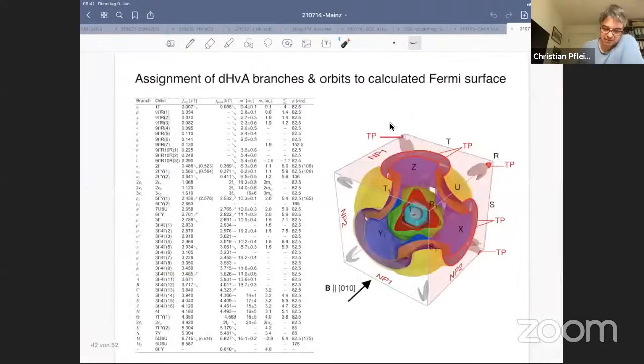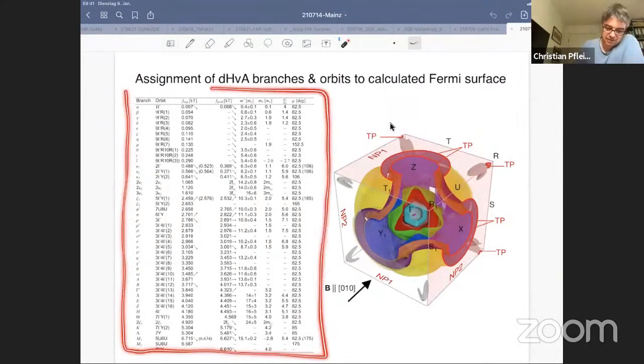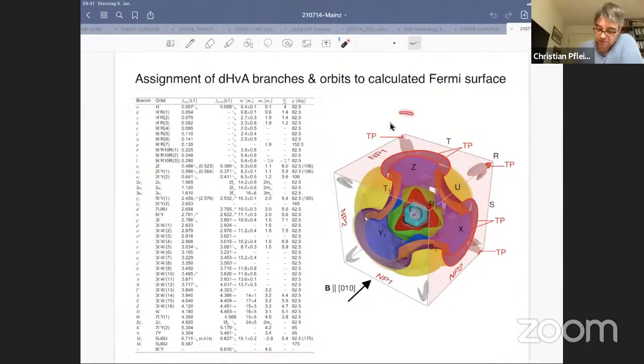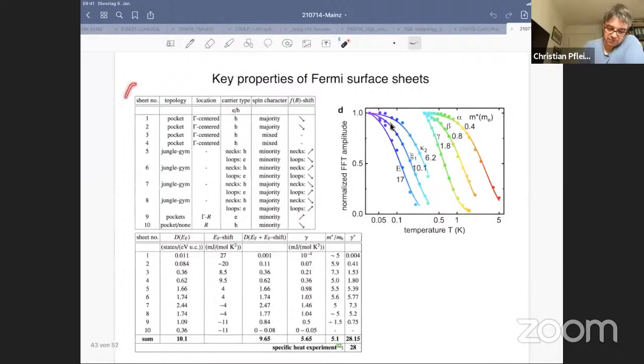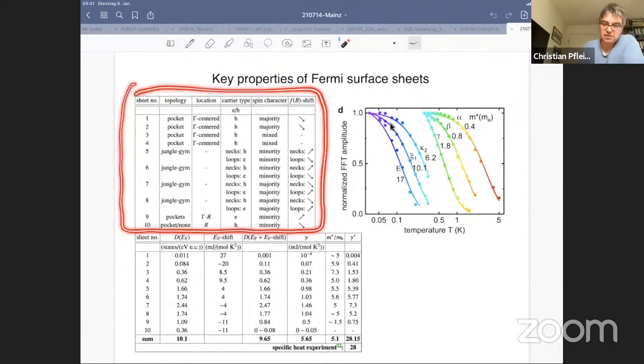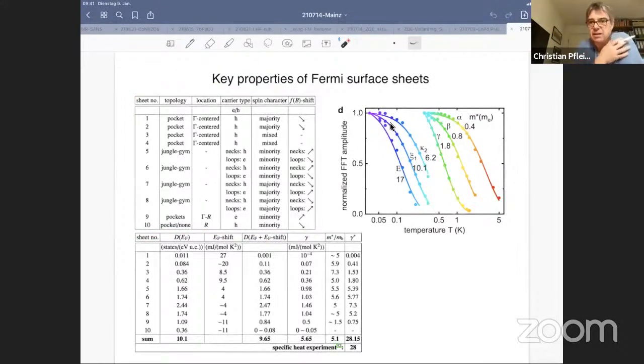So for doing that, here's a list of all the frequencies, and they can be fully assigned to these types of, we have 10 sheets of the Fermi surface. And once you go through this, you find that there are some sheets which are centered on the gamma point, some sheets which are centered on the R point, so you can sort them out. And then you have some sheets which are centered on the gamma point, which basically hit the Brillouin zone, and so they cut through the nodal planes. And these are the ones that we want to focus on. So the assignment has been fully done. You can tell for these 10 sheets whether they're electron and hole pockets, and what kinds of character they have.